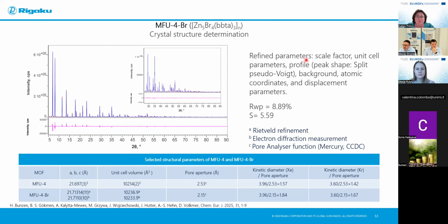Here you can see the refined parameters, Rietveld refinement plot, as well as the residual plot here at the bottom. And Rwp in this case was below 9%. We also proved that the obtained unit cell parameters from different methods, like from electron diffraction and also from powder data, were very, very similar.